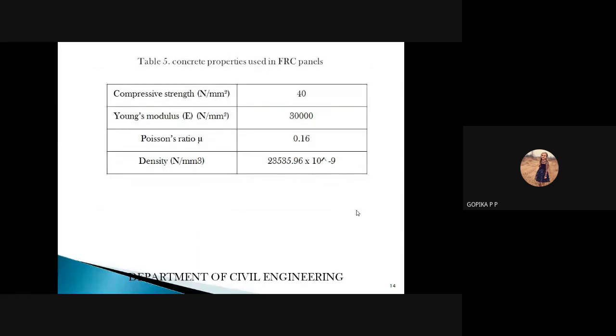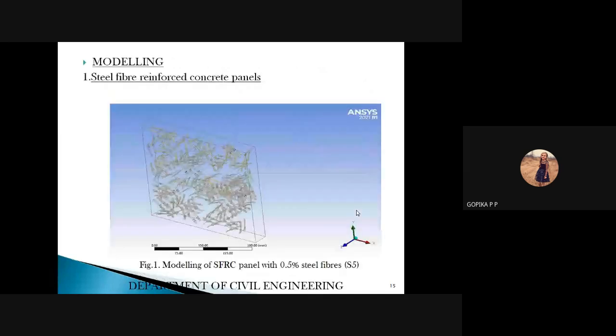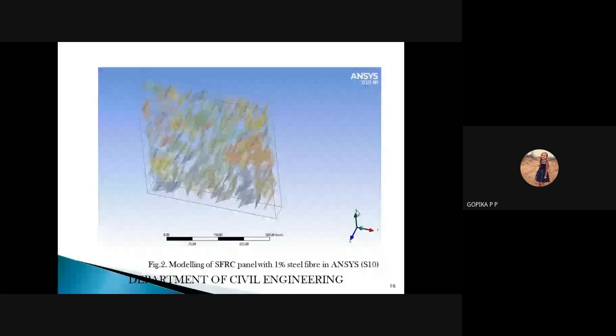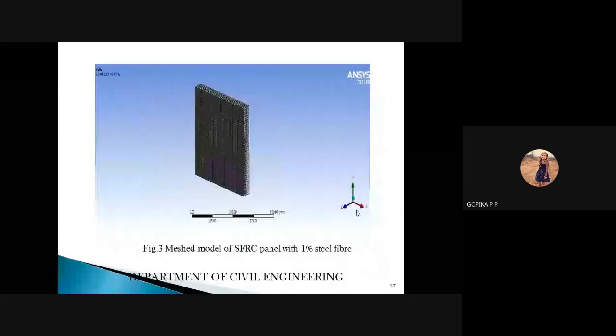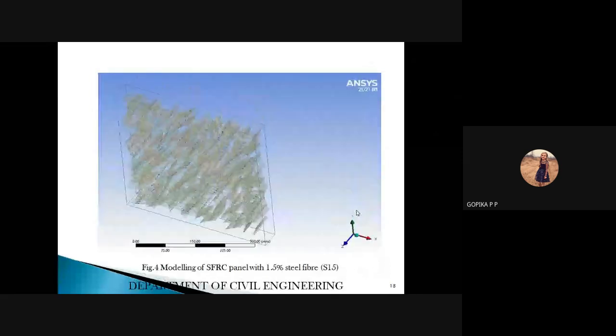This table shows concrete properties used in FRC panel. Compressive strength is 40 Newton per mm square, Young's modulus 30,000 Newton per mm square, Poisson's ratio 0.16, then density 23,535.96 × 10⁻⁹ Newton per mm cube. Next is modeling. This figure shows the modeling of SFRC panel with 0.5% of steel fiber. This figure shows modeling of SFRC panel with 1% steel fiber in ANSYS. Then this is the meshed model of SFRC panel with 1% steel fiber. This figure shows the modeling of SFRC panel with 1.5% of steel fiber.